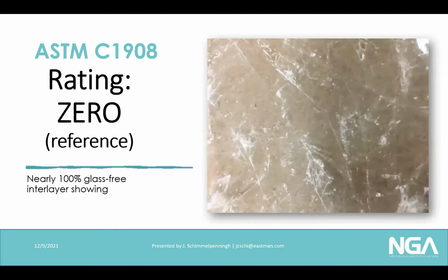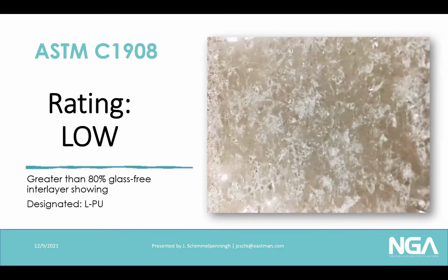But the ratings look like this. This is a rating of 0. This is not actually a rating, it is a reference. And you can see the large areas with nothing but some glass dust on the surface of the interlayer. This is a low rating, and you can see that there's about 80% free interlayer to the glass. The white parts are the glass parts that are still on.